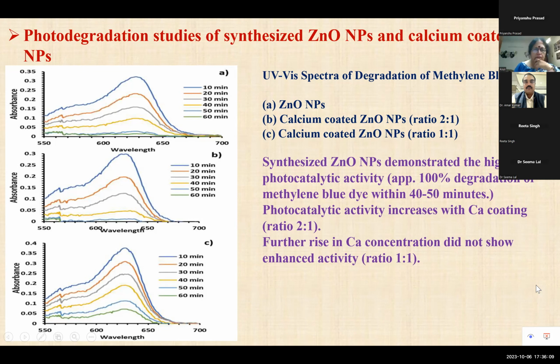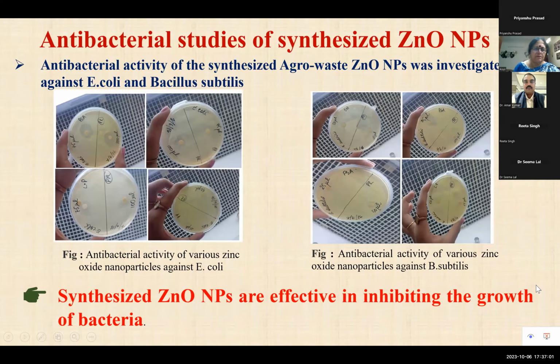Okay, ma'am. This is the effect of zinc oxide nanoparticles and its calcium nanocomposites on photodegradation of methylene blue dye under natural sunlight. Synthesized zinc oxide nanoparticles demonstrated high photocatalytic activity with almost 100% degradation of methylene blue dye within 40 to 50 minutes. Photocatalytic activity increases with calcium coating when the ratio was around 2:1. But when we raised the ratio to 1:1, the activity didn't increase to a further extent. Now, antibacterial studies on the synthesized zinc oxide nanoparticles showed that they are effective in inhibiting the growth of bacteria.